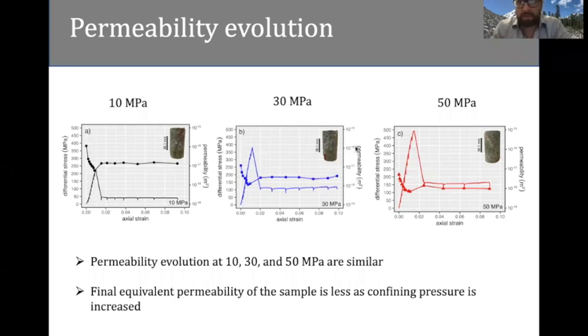So what we can see from the other experiments is, as we increase the effective pressure, that qualitatively the evolution of permeability of the sample is very similar. We see decreases in permeability here and here as we are loading the sample to the peak stress. We see increases in permeability of the sample following the formation of the macroscopic shear fracture.